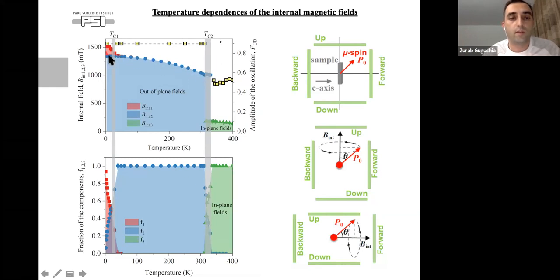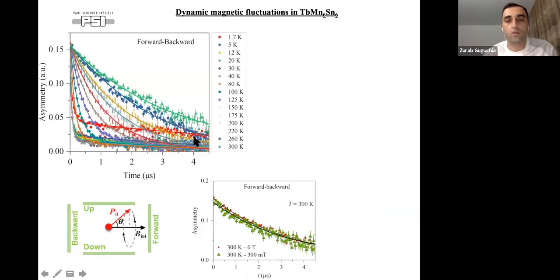And so we have the out-of-plane fields, but then we have another frequency below 25 Kelvin, which is higher than the frequency which we got at room temperature. Interestingly, we again have a volume-wise competition between these two components below 25 Kelvin. Okay, so if we had these out-of-plane fields truly static, then we should not see any signal or depolarization on the forward-backward detectors. But instead, we see a strong depolarization, no oscillations, but strong damping.